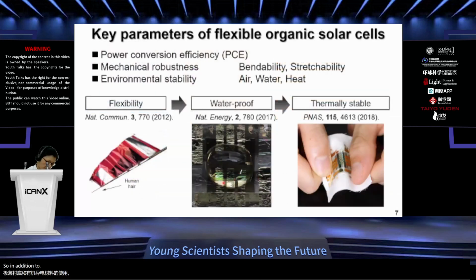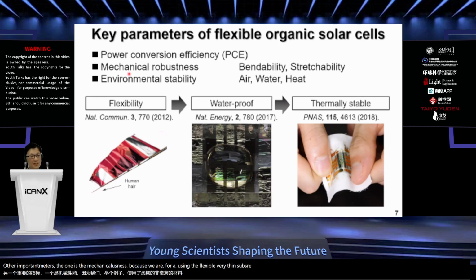So in addition to the increased power conversion efficiency, PCE, there are other important parameters. One is mechanical robustness. Because we are using a flexible, very thin substrate, flexibility is a very important parameter. So we try to improve both the efficiency and the mechanical robustness, such as bendability, or in some cases stretchability, which is another important parameter. The second important parameter is environmental stability. We need to solve the instability problems against many environmental factors such as air, oxygen, water, or thermal stability. We need to solve these environmental stability issues even when we use a very thin substrate.